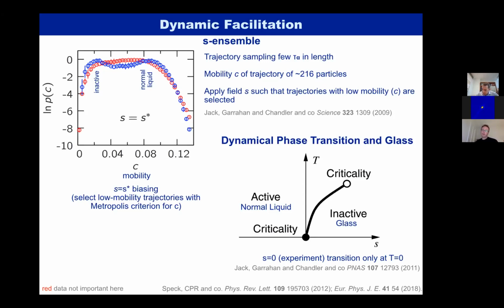So if we think about another way to interpret this theory, that is shown on the graph in the bottom right. Now I need to tell you about this quantity S. We can think of S as a biasing field. That is to say, we tend to sample towards inactive trajectories if we have a positive S. The reason for that is that, when I showed this blue movie initially, it turns out that there are relatively more trajectories which are moving fast. So we use S to sample the system towards the glass. It's like tilting the distribution of trajectories towards the glass.